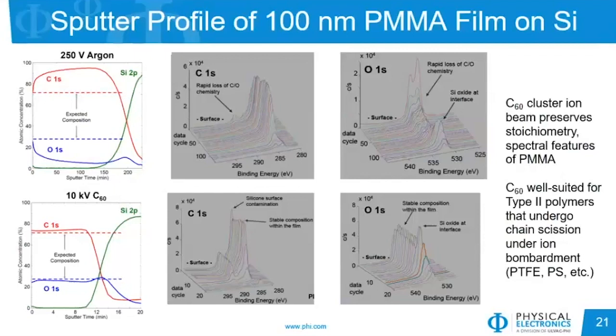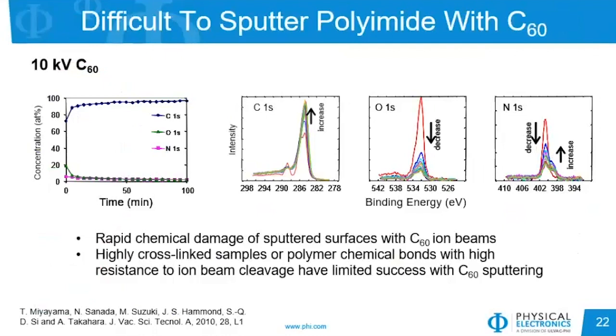This is an example of a type 2 polymer that is well suited for C60 profiling. These are types of polymers that undergo a chain scission type of breaking up under ion bombardment, such as PTFE, polystyrene, and others. However, polymers that are considered type 1, such as polyimide, can actually cross-link under ion beam bombardment. And when doing so under a C60, that can make it difficult to actually clean or sputter these materials. As you see here in the plot on the left, we have a polyimide film that upon sputtering, we decrease our oxygen concentration, increase carbon, and we're not able to actually sputter through this film.